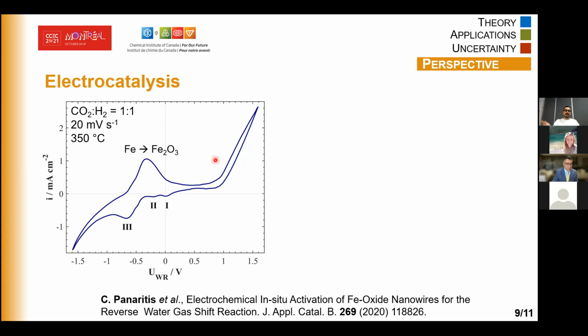When we return back, we reduce the catalyst back into its reduced form. We go through 3 different stages, where first Fe2O3 is reduced to Fe3O4, Fe3O4 to FeO, and then FeO to metallic iron, while at the last step, CO2 electroreduction takes place. So even if there was no catalyst, or there was a catalyst, CO2 could be split by itself at this range.